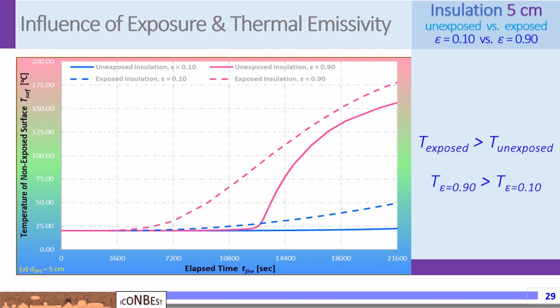Within this framework, the following graph highlights that a different wall insulation layout subjected to a fire curve shows a remarkable effect on the temperature response rate and the heat flow through assemblies of masonry walls. It is essential to point out that the above behavior corresponds to a flammable thermal insulation layer, an EPS, with a thickness of 5 cm. As seen, by placing the insulation on the non-exposed surface of a brick layer, the continuous blue and red lines exhibit a more suitable thermal behavior in contrast with the placement of the insulation on the exposed surface, the dashed blue and red lines. So, the unexposed placement of the thermal insulation layer reduces the rate of temperature rise, but still faces critical challenges, as the influence of the thermal emissivity is the key factor of a proper design regarding the influential and severe effect of a fire action.